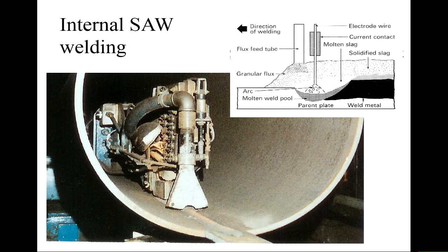So what you do is protect that. In the submerged arc welding process, we feed this granular flux onto the surface. So we have a big thick layer of granules of particles that when they get hot, they will give off gas that protects the surface, that doesn't allow that surface to oxidize. And they will also melt and become fused with any oxides that do form, and they'll form a solidified layer called a slag on the surface.